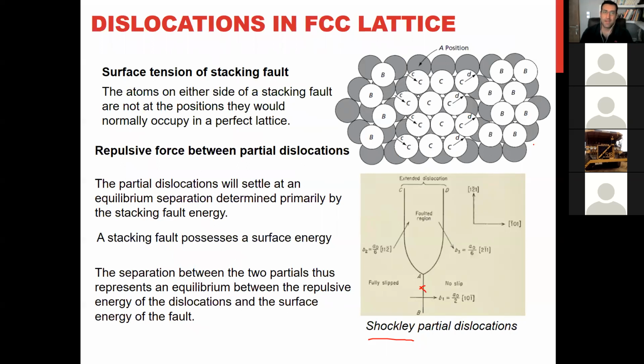So here we have two partial dislocations in an FCC crystal that make a stacking fault, and the schematic is like this. These two partial dislocations are separated. How many atoms or how many planes are between these two partials? It can be very narrow, or can be like this. This depends on two factors, and it is different for different metals. One factor is the repulsive energy that these dislocations have. They want to escape from each other. So we have a repulsive force between these two partial dislocations that separates them from each other.